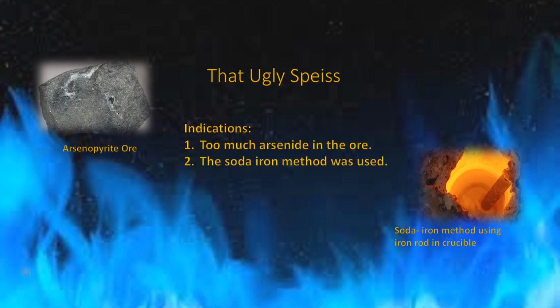The other indication is that of human error. The soda-iron method of fusion was selected. Ores that contain copper, nickel, arsenic, antimony, tellurium, and/or cobalt should never be treated using the soda-iron fusion method. These ores require the litharge-niter fusion method to be used for the collection of your precious and noble metals. If you're not sure of the constituents of your ore or concentrates, use the litharge-niter method, as it's still the best method to use.